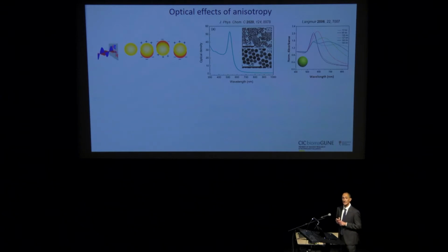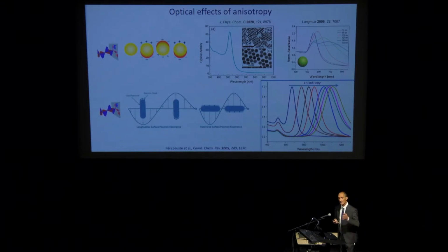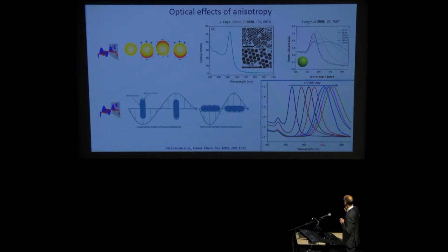However, one of the most exciting properties of these materials is that particle size is not really the most relevant effect. It's actually anisotropy, which can be used as the handle to very finely tune the wavelength at which there is coupling between light and matter. And so by elongating nanorods, for example, you can finely tune the position of this band from the visible all the way into the near infrared, even into the mid-infrared. And so by doing that, you can really select the material that you want to apply for any of the applications that you have in mind where a specific wavelength of light will be of interest. And so it's actually quite interesting to work and understand the chemistry behind the fabrication of materials with such an exquisite control of particle size and morphology.